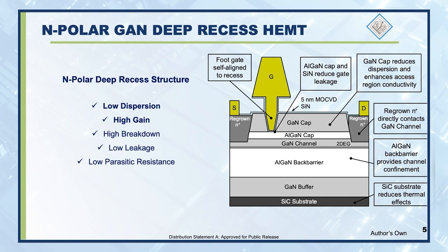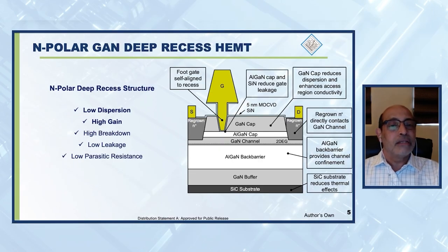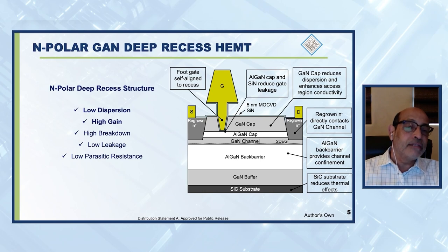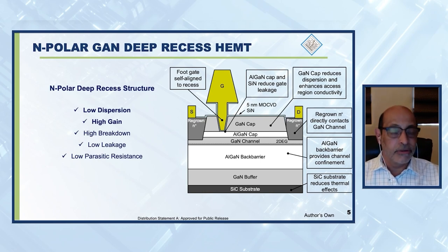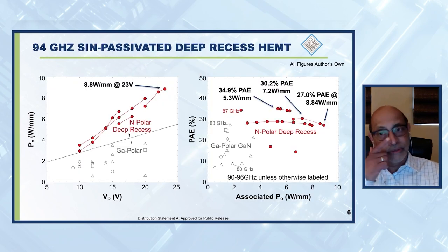Lastly, we have an MIS gate, an insulator under the gate, which, when coupled with the aluminum gallium nitride cap, reduces the gate leakage and gives you very high breakdown. So this rather complex structure actually addresses all the frailties of the gallium polar device, and therefore we end up with very high performance. What is the kind of performance that we achieve?